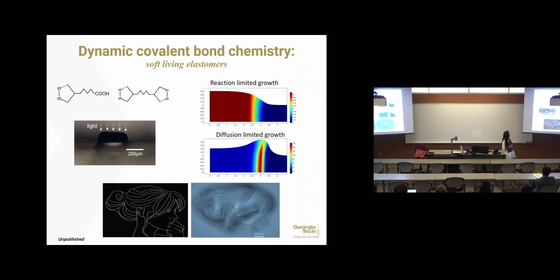Okay. And we also tried a different chemistry with this idea. Now using this, we can do radical polymerization. So we can use light to control the growth. We can do local growth. And the interesting thing is, because we have this model that can help us to understand the kinetics and the morphology coupling in the material. So you can see this is an axisymmetric simulation. The light is shining in this region.